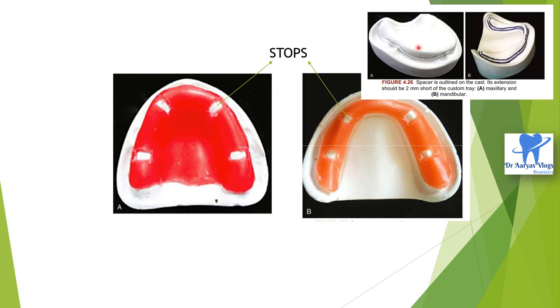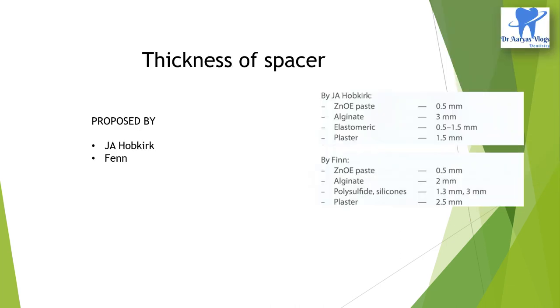So we have already said the spacer extension should be 2 mm short of the custom tray. What is the thickness of a spacer? According to various authors, there are various dimensions. The main authors who described this thickness of spacer are Hopkirk and Fenn. The required thickness of a spacer was proposed by J.A. Hopkirk and Fenn. By Hopkirk, zinc oxide eugenol paste 0.5 mm, alginate 3 mm, elastomeric material 0.5 to 1.5 mm, plaster 1.5